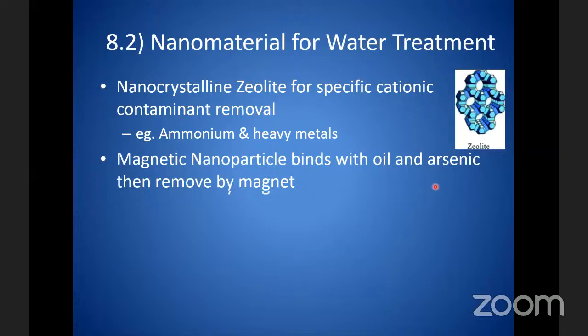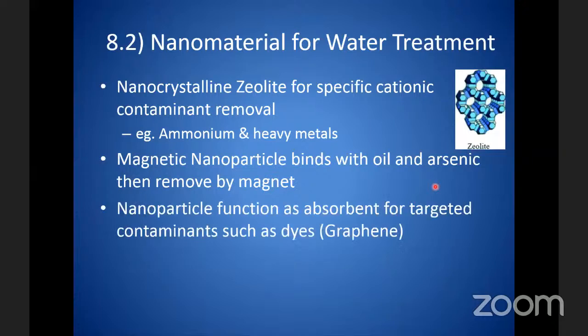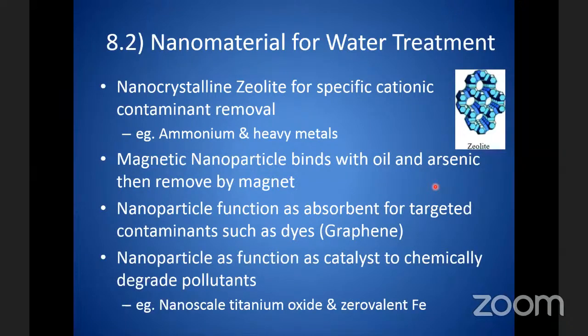Right. Some are magnetic nanoparticles that bind with oil. It will remove the oil and arsenic. Then the whole thing we can separate by magnet. Nanoparticles function as absorbents for targeted contaminants such as dye, by this graphene. Graphene is a nanoparticle. Nanoparticles can also function as a catalyst to chemically degrade pollutants, like nanoscale titanium dioxide and zero valent iron. Those are the things they can use.